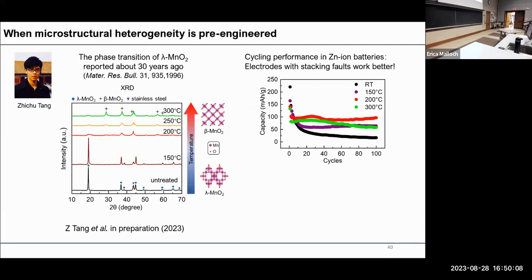Then what if we start to pre-engineer the microstructure even before we use the particles in the system? This is the idea adopted by my PhD student Zhi. He dived into some really old literature from about 30 years ago, which shows that manganese oxide particles can undergo a series of phase transformations when you heat them up, shown in this XRD result of his. He was then able to show that differently pretreated nanoparticles indeed have different performance in zinc-ion batteries.